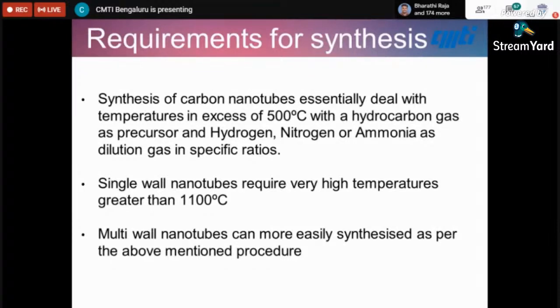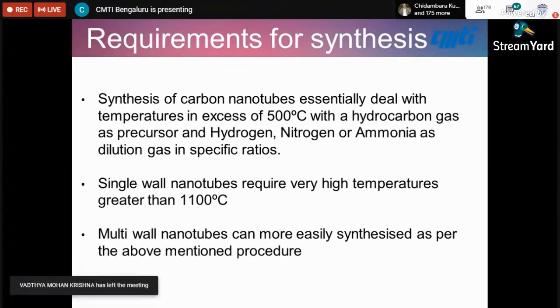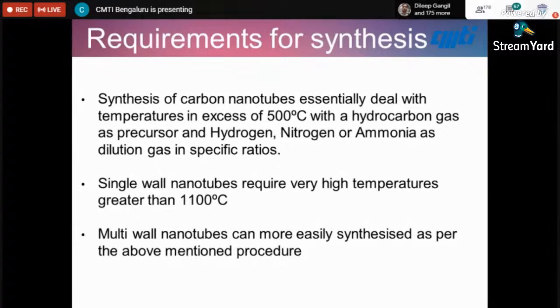So what are the requirements that you need to synthesize carbon nanotubes? This is quite important. First of all, you need to keep ready a vacuum chamber which can go up to temperatures greater than 500 degrees centigrade. Then you have a hydrocarbon gas, like either methane, acetylene, or ethane, and then you use a dilution gas such as hydrogen, nitrogen, or ammonia in specific ratios. Typically for growing CNTs, the ratios of hydrocarbon to dilution would be 1:3, 1:5, 1:8, 1:12, and so on. And as I already said, multi-walled carbon nanotubes are more easily synthesized as per the procedure that I'm going to share.